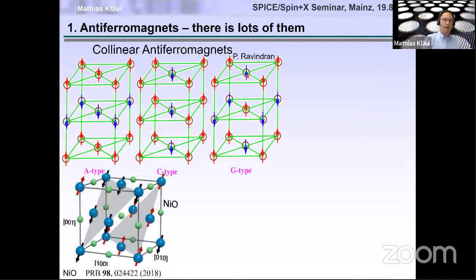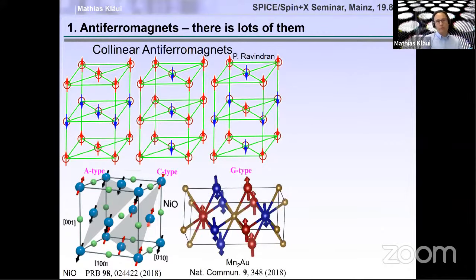And actually, these types of differently coupled antiferromagnets exist in reality. This is, for instance, nickel oxide, which is a layered antiferromagnet where the 111 planes have the sublattices pointing in one direction, and in the neighboring 111 plane, the spins of that plane point in the opposite direction. So you have a fully uncompensated layer, but all the layers compensate each other, and you cannot distinguish between the layers. Then here you have manganese gold, which we're going to talk a bit about in the future. Manganese gold is quite special because it actually has sublattices that you can distinguish, and this is very important, as we'll find out later.